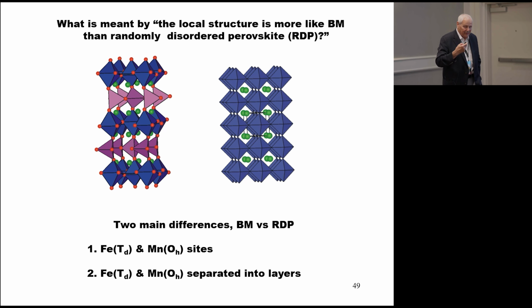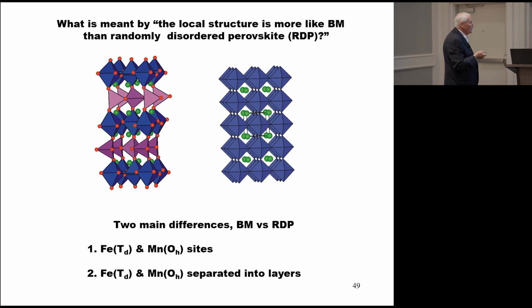So let's just briefly examine what's going on with the small box approach. Is there any sense at all in talking about a local Brownmillerite structure? Is there any part of the local structure that looks even remotely like a Brownmillerite? And so we can examine that again with the PDF results. There's two main differences between the randomly ordered, distorted perovskite, and the Brownmillerite. Of course, there are specific sites for iron and manganese ions, and they are separated into layers. The specific sites are octahedral for manganese, tetrahedral for iron.